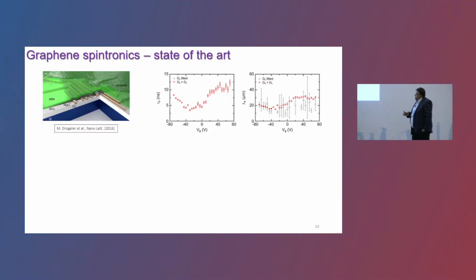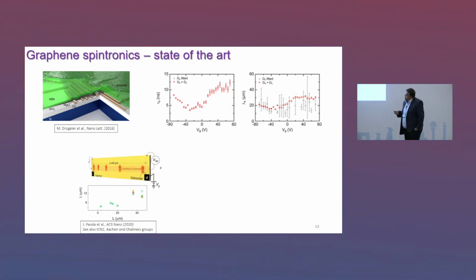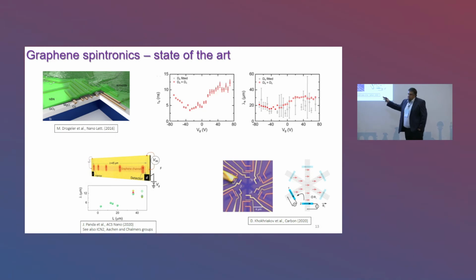Those results were good, but it was still about three orders of magnitude smaller than the theoretical expectations. So the field has been pushing the efforts much more, and for example, it is now shown that the spin relaxation length in graphene at room temperature can exceed 30 microns, which is the highest ever measured in any material system. And this can also be realized in large-scale graphene, and a group in Sweden has already demonstrated that you can make some basic spin circuits using graphene.